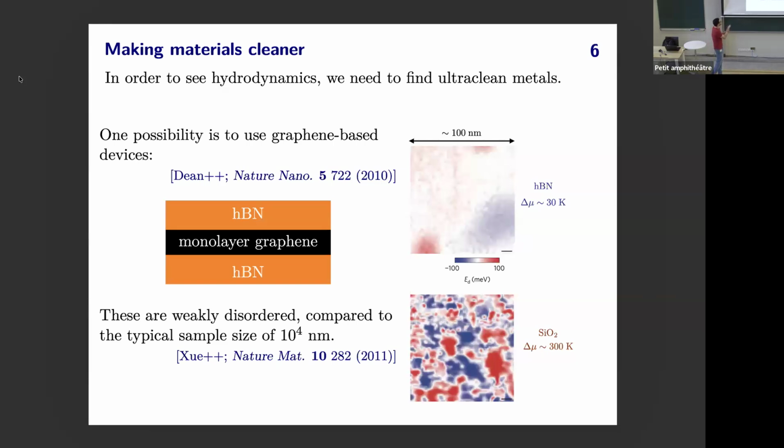In a nutshell, the old way people used to grow these materials led to a lot of chemical bonding between the atomic graphene layer and the substrate. You can't suspend a single membrane of carbon in a stable way, just mechanically, right? So usually you want to put it on something to make it more stable, but if it's silicon dioxide, that just bonds with graphene, and it's kind of lousy.